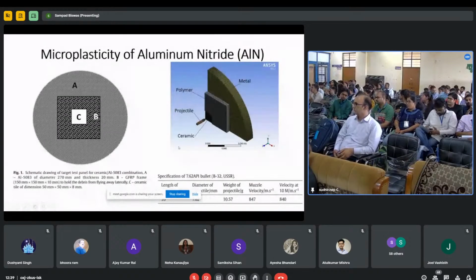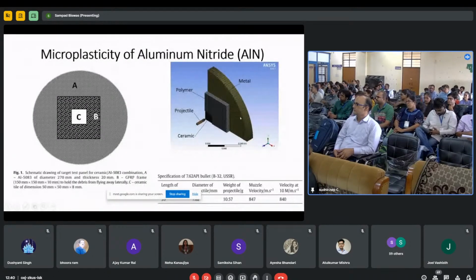Now this is the target which we took. This target is made up of aluminum alloy A, on which we have placed a fiberglass material which is surrounding the ceramics. This ceramics is denoted by C. Then this C portion is hit by the bullet, and later on we have modeled it in the numerical simulations, and we did the work.